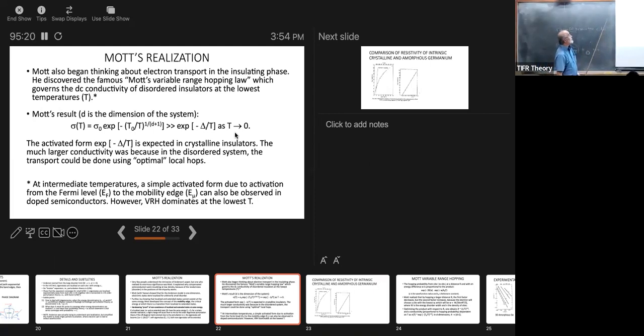So Mott actually also began thinking about the electron transport in the insulating phase. Once he accepted the existence of the insulating phase, he discovered what's known as Mott's variable range hopping law, which governs the DC conductivity at low temperatures. And it turns out that it has a very strange form. It's not like in a normal insulator where you have a prefactor and an exponential of minus some gap divided by temperature. It's, in fact, in 3 dimensions, exponential of minus (T naught over T) to the power 1 over 4. In 2 dimensions, it would be 1/3. In 1 dimension, it would be 1/2.